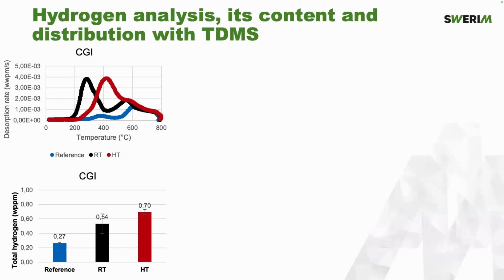So if we look into the CGI, here on this slide, you can see on top the TDMS spectra that describe reference material, which has not been tested. And the black and the red curve represent measurement of hydrogen after room and high temperature SSRT testing. So you can see definitely a different distribution of hydrogen affecting at room temperature, namely weak trapping sites, and as well at high temperature, strong trapping sites. If you look into the content levels that we measured, rather logical. So we see uptake, but the main difference is which sites we occupy. And this also supports the SSRT measurements.